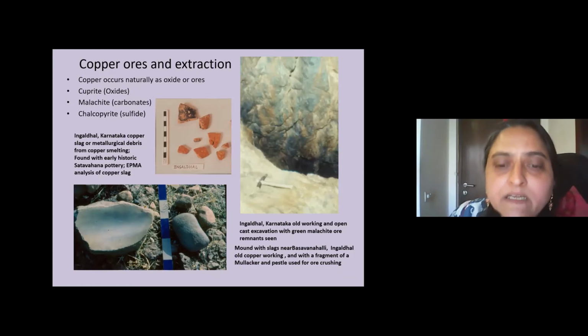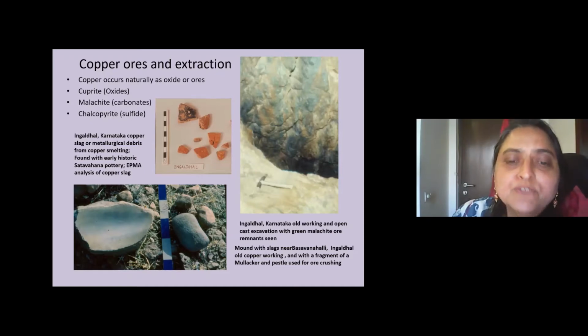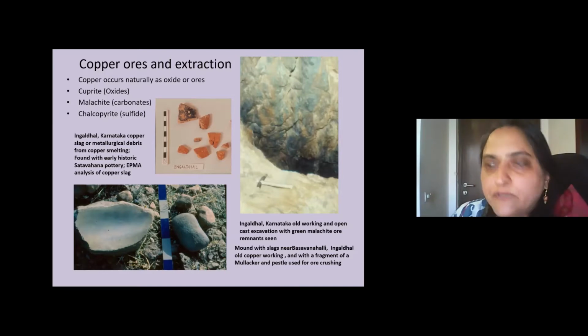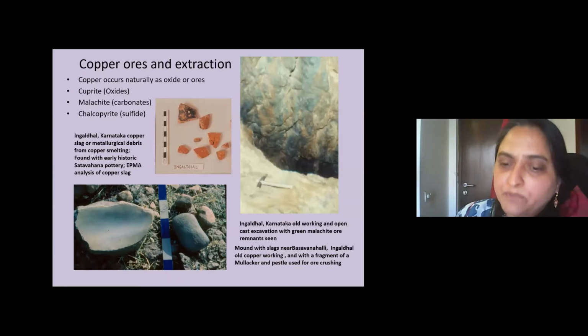And typically, once the metal is extracted from the ore, in this case malachite or copper carbonates, it undergoes a smelting or reduction process. And typically what you do find in terms of the debris are these slag heaps, in which the slag is the impurity which floats on top of the furnace, where all the siliceous impurities and the gangue go into the slag, and then the smelted metal goes into the bottom of the furnace.